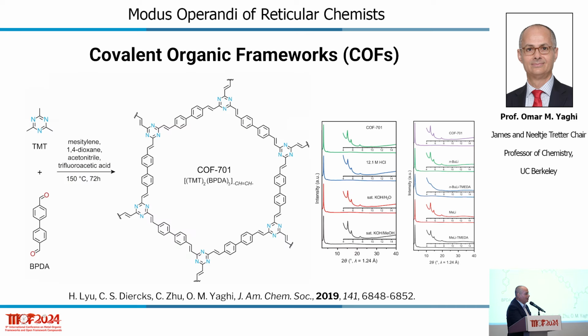You go to COFs. This COF is made from carbon-carbon bonds. Who among us dreamt that we can make COFs from carbon-carbon bonds, crystalline? It's an impossibility, but this is now possible. And you can see that this material is stable in 12 molar hydrochloric acid, saturated KOH, and even n-butyllithium, such corrosive solutions. This is the material that you want to use for air capture because it's stable and potentially it can stay in the device for many, many years.